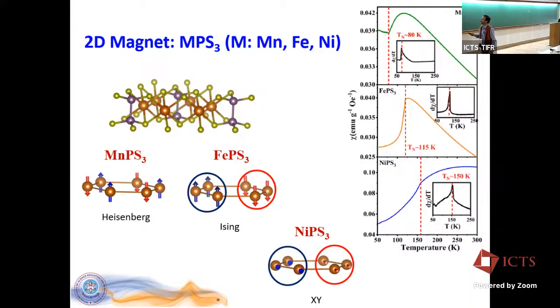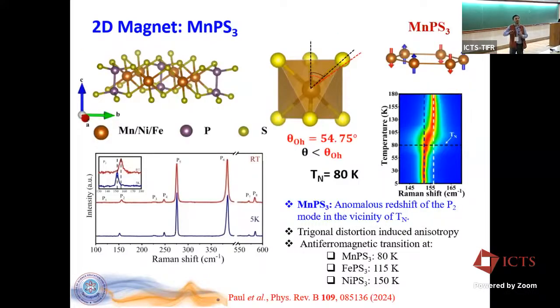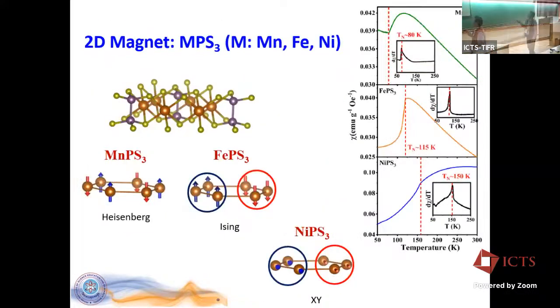And if we look at the spin orientations, in MnPS3 the nearest neighbors are antiparallel, all right? In FePS3, this set of 3 are ferromagnetically ordered, and this set of 3 are ferromagnetically ordered, but compared to each other they're antiparallel. So if you look at the chain, there is a zigzag chain which is ferromagnetic, there is another zigzag chain which is ferromagnetic, but these 2 ferromagnetic chains are antiparallel, and that's what gives the antiferromagnetism in FePS3. Similar is the case for NiPS3, but here the spins are in plane, okay? In the other 2 cases, they're out of plane, and here it is in plane, and that's where the story is all about.